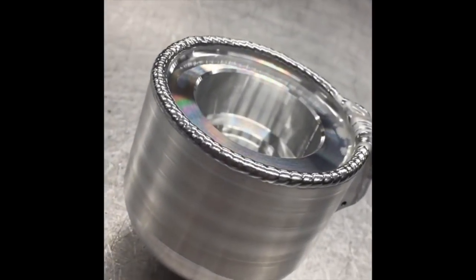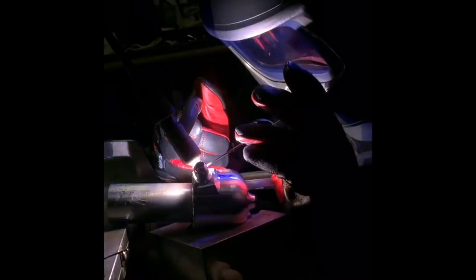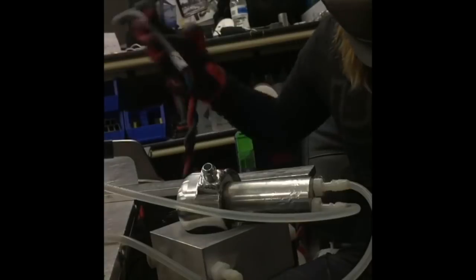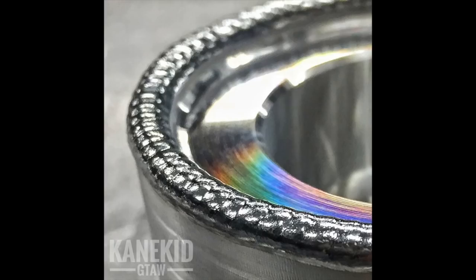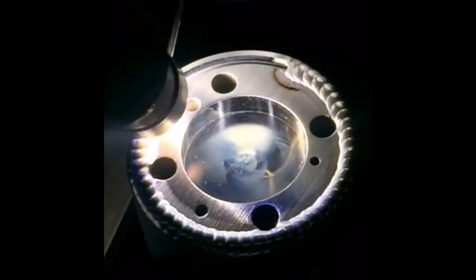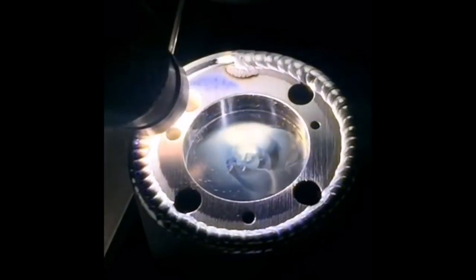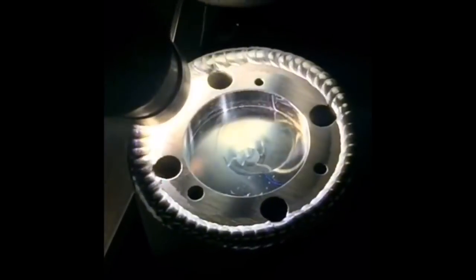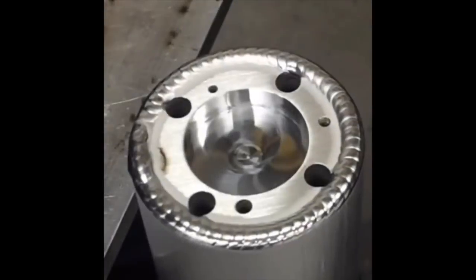So on the thin wall stuff, the thinnest material I weld on is 6 thousandths wall Inconel and 8 thousandths wall stainless steel. Pretty small. Prepping those, I'll step down to 1 millimeter or 0.040 inch tungsten. I like using the 2% lanthanated. I recently got a pack of the Lava alloy from CK because it has really good repetitive start and micro arc start capabilities. I've yet to use that alloy, but the 2% lanthanated I've been a big fan of so far. It seems like a harder tungsten. It's more heat resistant than some of the others.